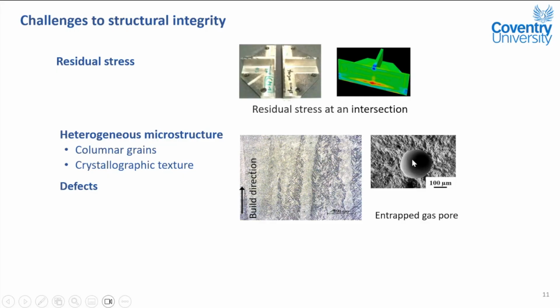Then the third one is defects. By optimizing the process parameters, lack of fusion from low energy and keyholes from excessive energy can be controlled after so many years of additive manufacturing research. But one defect that cannot be completely eliminated is entrapped gas pores. So we will always find these. Are they critical to fatigue? This has been my research topic.